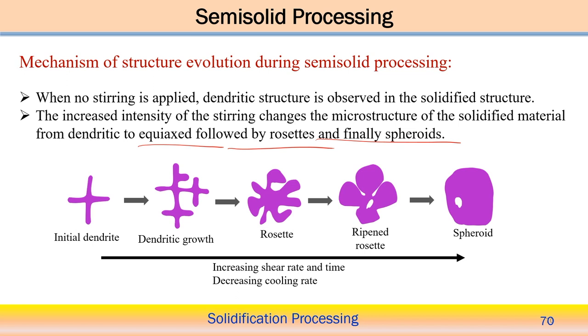In this case, we try to understand in what way the structure is formed in semi-solid processing, because in semi-solid processing we always apply some kind of shearing action. This shearing action helps to change the structure. So initially dendrites form. We can see the initial dendrite, primary dendrite or secondary dendrite, and then we can see the dendritic growth. It forms a kind of network. I am talking about the second figure, where after a certain period of time dendritic growth occurs.